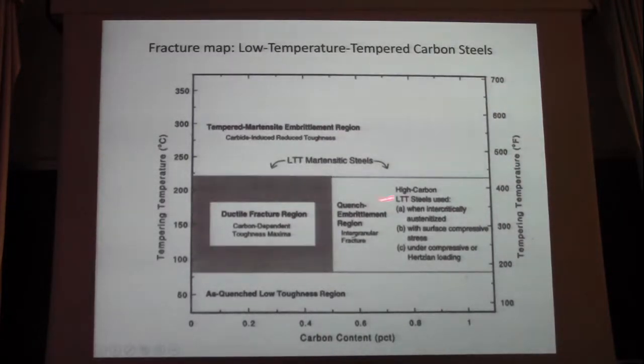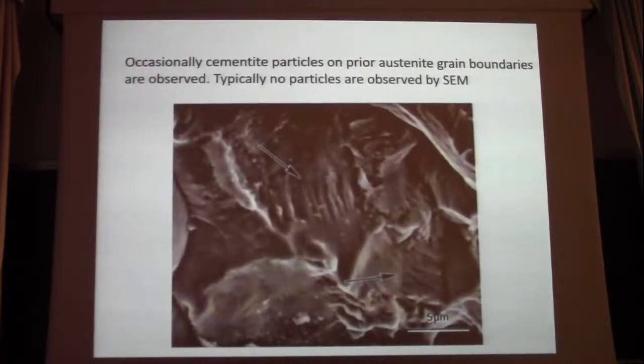Here's another map, part of the map. This is tempering temperature, and this is the critical range for high strength, basically between 100 and 200, 175 C. And you get ductile fracture here. So if the carbon content is low or medium, there's not a major consideration. But if you go over 0.5%, you get the quench embrittlement, and you get this structure. Now, the grain boundaries, these intergranular fracture surfaces, in scanning electron microscopy, you just don't see anything.